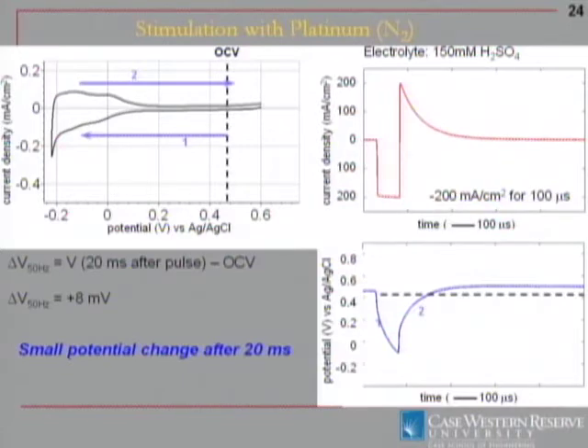Okay, so here's some results from that. And again, this is now a 100 microsecond pulse. This is, of course, much more relevant for stimulation purposes. We've put the slow scan Voltammogram, which is taken on the order of seconds, for comparison to show you where we are in that potential window. This is actually a narrow window where, again, you don't see as much of that hydrogen adsorption and desorption that you'd see on a typical platinum electrode in PBS.